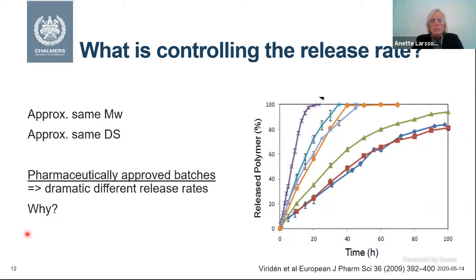But here comes an example from our group where we have the polymer released as a function of time. These are 7 different batches of polymers. And in pharmacy, it's very critical that all stuff you use is pharmaceutical approved. So to get it pharmaceutical approved, you set up criteria, what parameters that you should test, and they are tested for all batches. So when they are pharmaceutical approved, they should be the same.